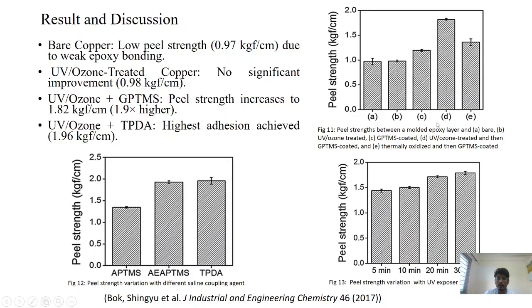Peel strength is the amount of force which is required to peel the epoxy from the copper substrate. So in case D, the peel strength is higher, because in this method UV light is implemented along with the silane coupling agent. In this method the peel strength is 1.82 kgf per centimeter, which is 1.9 times higher as compared to the bare copper. After that, in this figure, APTMS and TPDA, these are the silane coupling agents,